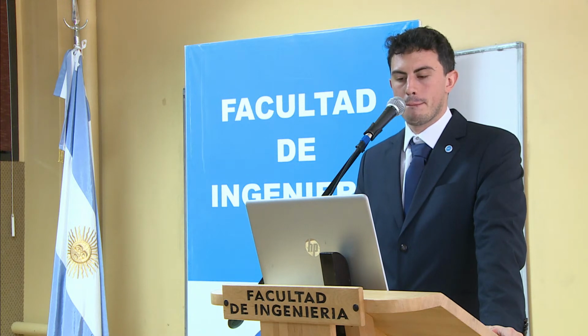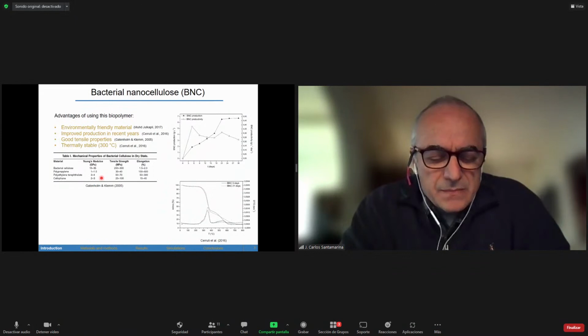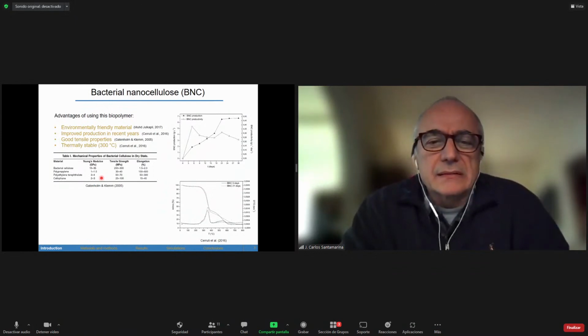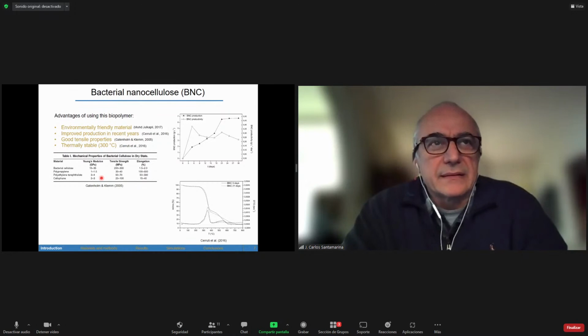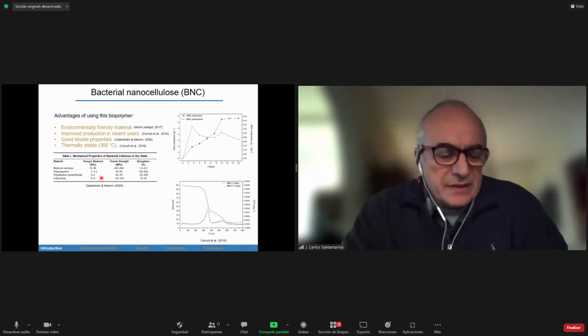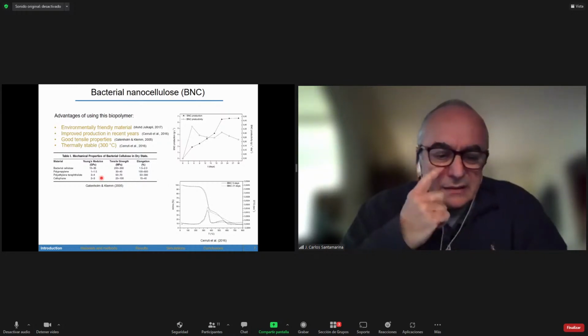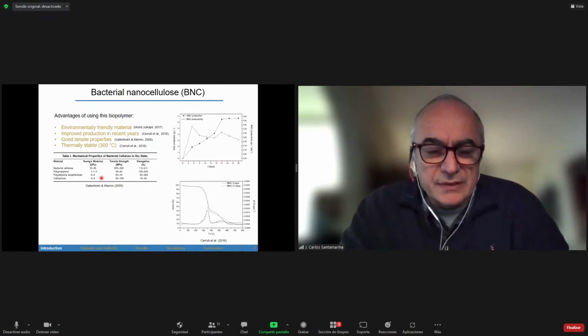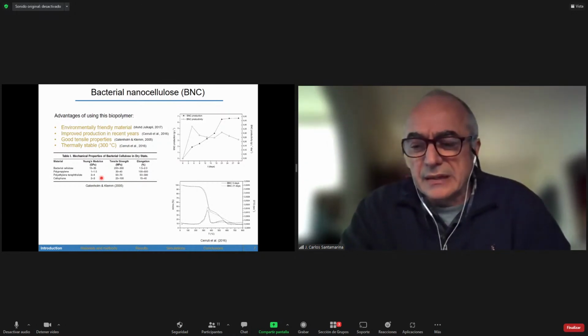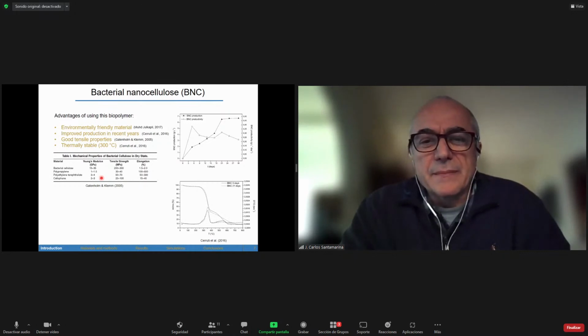Okay, Juan Cruz, you say a few times, 5 or 6 times throughout the thesis, that given the high specific surface, it absorbs much water, and that has an important effect in further hydration, etc. And clearly it changes the viscosity, and there are equations that we can use to compute the changing viscosity due to the addition of high specific surface material. But you clearly show that in your thesis as well.